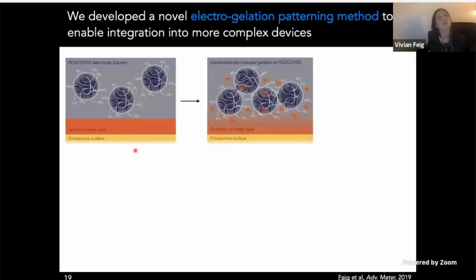On the other hand, if you want to have more miniaturized devices that might include multiple layers or materials or components, then we want a different type of fabrication method besides molding that might be more amenable to these more complex device integration processes. And so to enable that, we wanted to see if we could come up with a method to better control the spatial deposition of our PEDOT:PSS gels on different surfaces. So we came up with this concept of using a sacrificial metal layer that we could oxidize in the presence of these PEDOT:PSS solutions, generating metal cations that would screen those repulsive forces between the microgel particles and get it to aggregate into a gel.